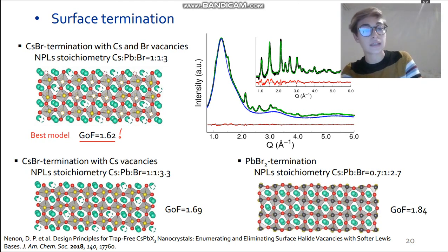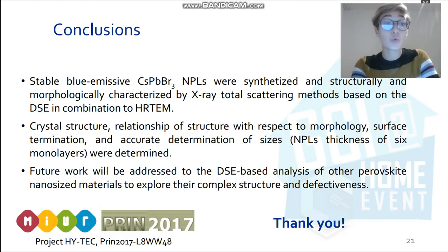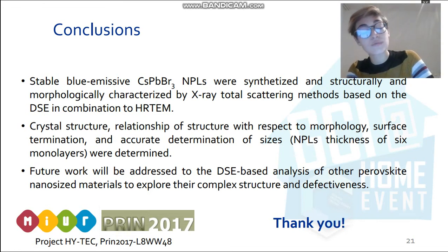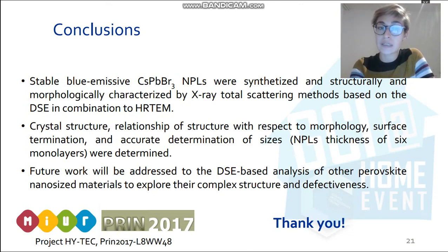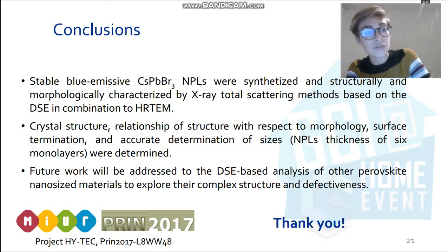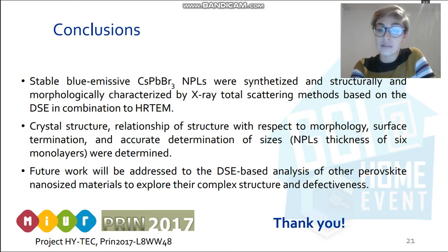To conclude, in this work I presented the synthesis and the full characterization of stable monodisperse 3.5 nanometers, equal to 6 octahedra monolayers, thick cesium-lead bromide nanoplatelets, and an accurate structural and microstructural characterization was provided. As future perspective, the results here presented encourage to extend this kind of analysis to other nano-sized materials belonging to the class of lead-halide perovskites.